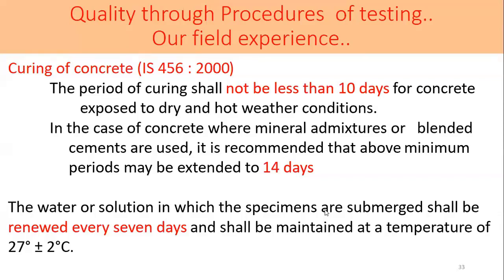Accordingly, the temperature of the water, that indoor condition, is not followed. When curing is done, the temperature is one criterion. If the cube is in a submerged condition in a tank, then the water in the tank necessarily should be checked every 7 days. This many times is not followed in the field. That hampers the quality of the testing.